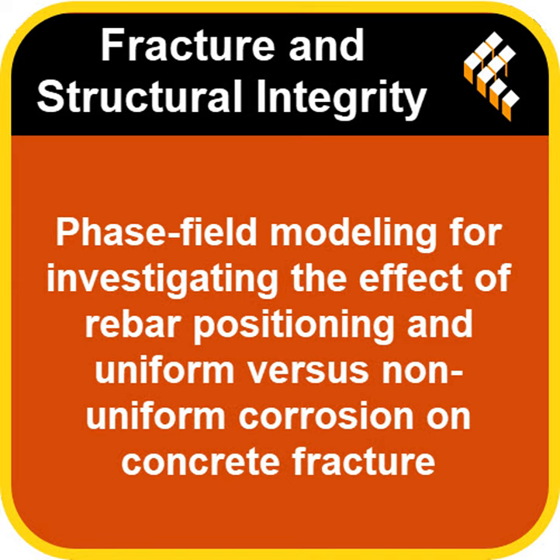Interestingly, for the corner rebars, they called this 4D10T2, the crack development was quite similar under both uniform and non-uniform corrosion. Really? After seeing the differences before? Yeah. In both cases, they saw cracks heading out towards the corners, as you might expect, but also cracks running parallel to the edges between the rebars. Which sounds like it would lead to the whole cover layer potentially detaching.